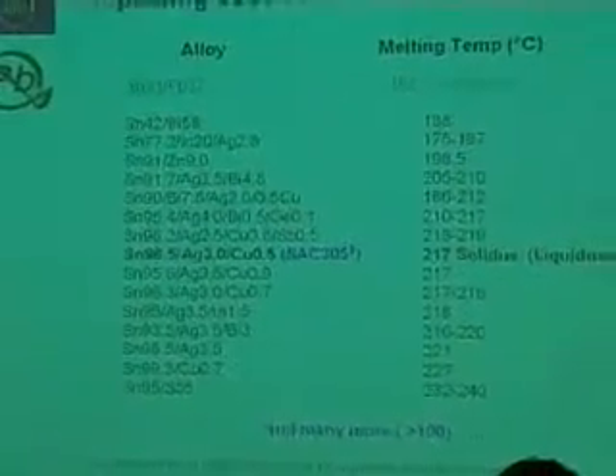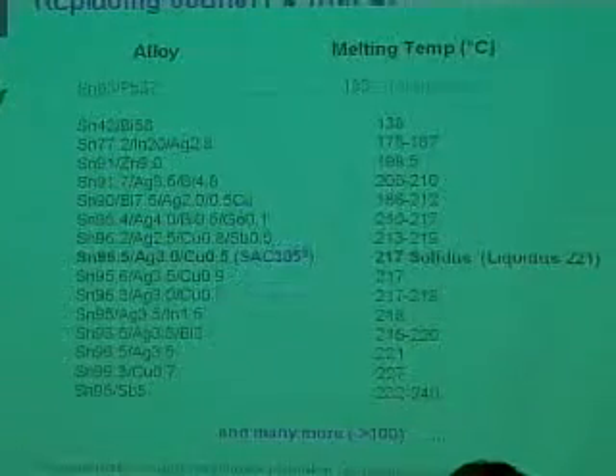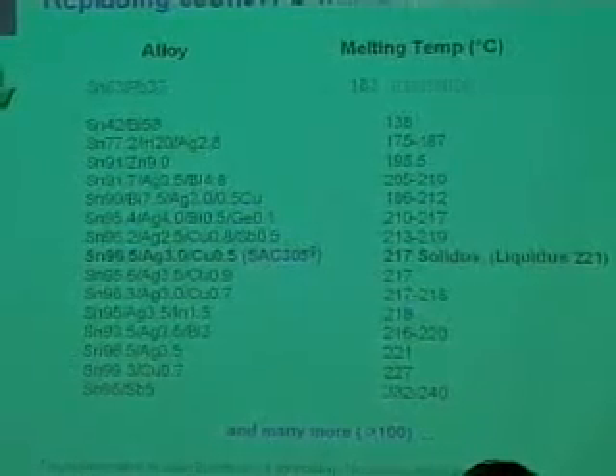And what we've largely, but not exclusively, come up with, or what we're now using, is this so-called SAC 305. It's 96.5% tin, 3% silver, half of 1% copper. And that is the solder that I think the majority of people are using now. There are other variants of the SAC solders where you might have 4% silver, or you might have 1% silver. The amount of silver that you put in there can affect the intermetallic growth, and by reducing silver, you may actually get an improvement in the shock tolerance in these solders.